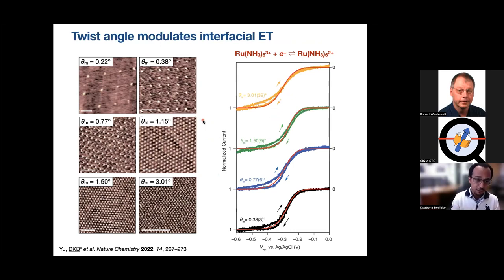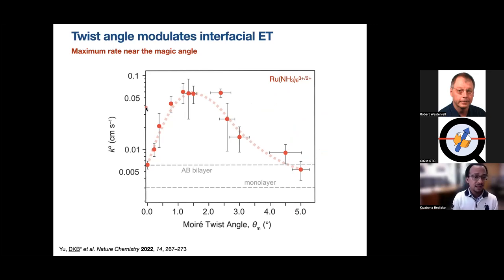And so we can go ahead now, and we don't just have one twist, we can make samples at different twists. And you can see from the STM data that we can control the twist angle from relatively small to relatively large. And so we can get our electrochemical data at each of these cases, and what we see is that there is a strong modulation of the interfacial charge transfer as you change the twist angle. So this is on a semi-log scale versus twist angle. And you see that the rate for this reaction increases quite significantly, over about an order of magnitude. And then in the vicinity of about 1 to 1.5 or so degrees, we measure this maximum rate, which is almost reversible electrochemistry. And then beyond that, it starts to drop off.